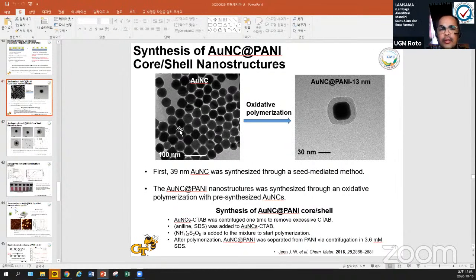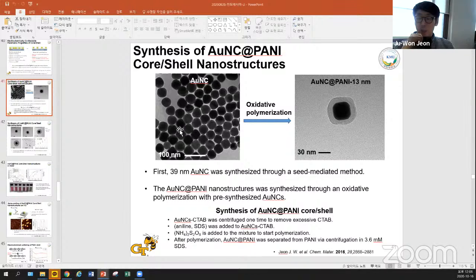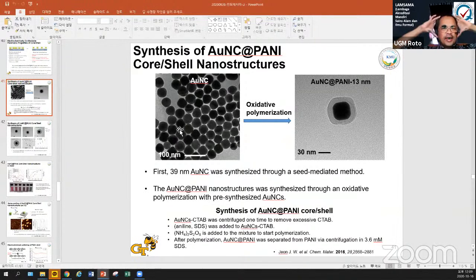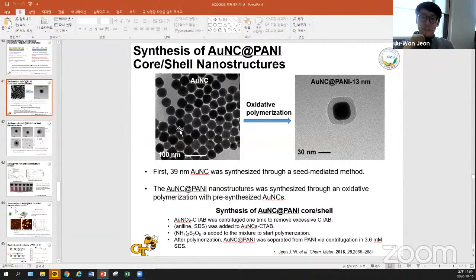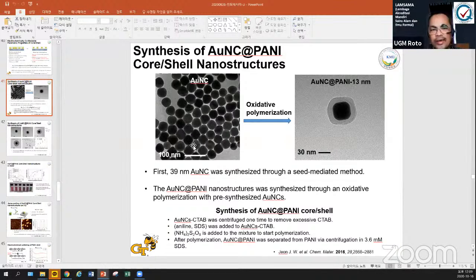Gold nanocubes can usually be synthesized by the seed-mediated method. The seed should be added into the solutions at the right timing and right concentration. There are a lot of recipes to synthesize gold nanocubes and gold nanorods, but the student should practice the morphology. It is a bit of a technique thing. Sometimes we have a mixture of cubic, hexagonal, and spherical, but you have nicely cubic, so that's what I want to learn. Actually, we got some help from other group members who have expertise.